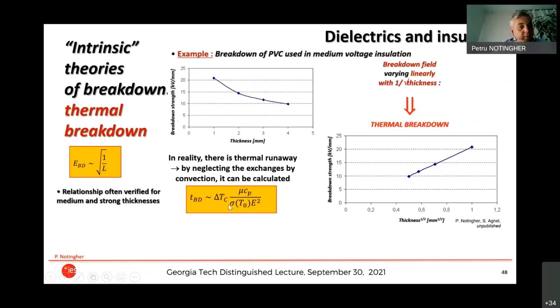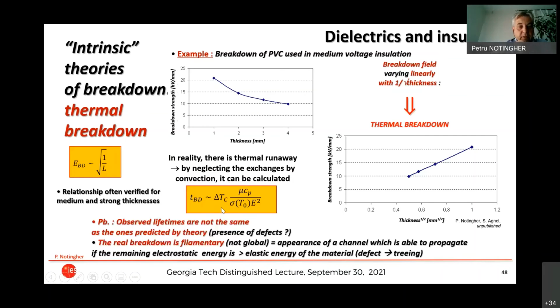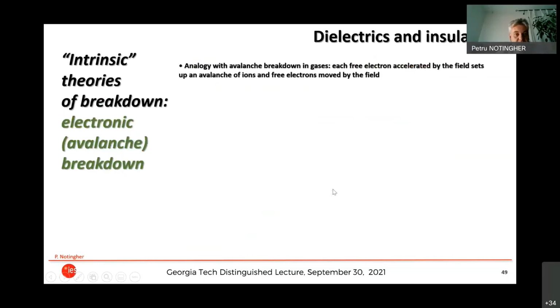You can even calculate the time to breakdown if you neglect the exchanges by convection by considering that there is a thermal runaway. But in practice, these lifetimes are not the same as what you predict by theory, and the real breakdown is not a breakdown over the entire material, but only over a filament. So it will not give you the good values, but the law of the breakdown strength with respect to the thickness would be respected.